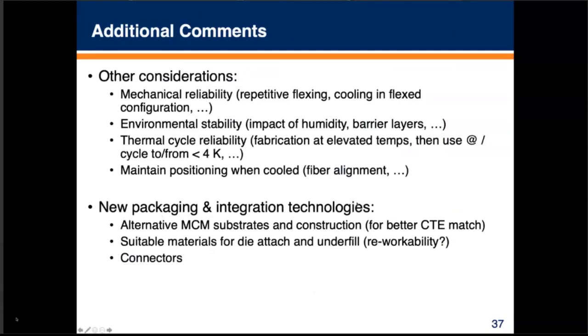Some new packaging and integration technologies, things that are on our radar, looking at alternative MCM substrates, as well as construction of those substrates for better CTE mismatch when you're looking at integrating more die onto these substrates and then taking them down to 4K. And then always looking for suitable materials for die attach and underfill, specifically if you start to think about needing to do reworkability on these. If you can imagine extending this to the superconducting quantum world where you might have an MCM full of qubits and one of those chips has problems and your others are your golden ones, you might want to be able to rework something. So reworkability is always something on our minds. And then you can see the connector structures that we've been looking at so far. There's still room for improvement on those by all means.